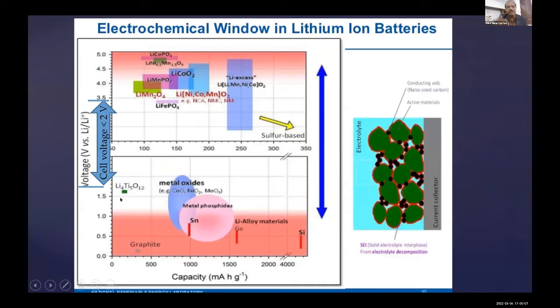So you can see here, there are various materials you use for batteries, in combinations. Here, lithium, if you take it as the reference, is 0, and versus 0 the cathodes are up, where you can choose. Lithium itself is not stable, so you cannot use it, for several reasons: dendritic growth when it is recycled and deposited back, and it is very sensitive to oxygen and moisture. So graphite is very close to lithium at the bottom, but its energy density is not so much. It's 340 milliamp hours per gram, but it itself acts like lithium and gives enough voltage.